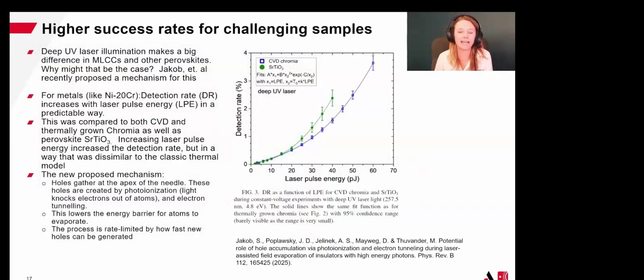Now, the best evidence that we have for increased success rates with perovskites is a new evaporation model proposed by Dr. Severin Jakob at Chalmers University of Technology. And we are in for a very special treat because he will be joining us for the live Q&A. Now, what the authors did in this case was compare UV and deep UV instrumentations with a couple of different materials. For metals like nickel chromium alloys, the evaporation should proceed in a predictable way. So as you increase laser pulse energy, your detection rate should also increase according to an Arrhenius evaporation model. And that is the case in deep UV and UV for metals, but not the case for certain kinds of oxides. Now, the authors here compared thermally grown chromia, so chromium oxide, and a perovskite material of strontium titanate.